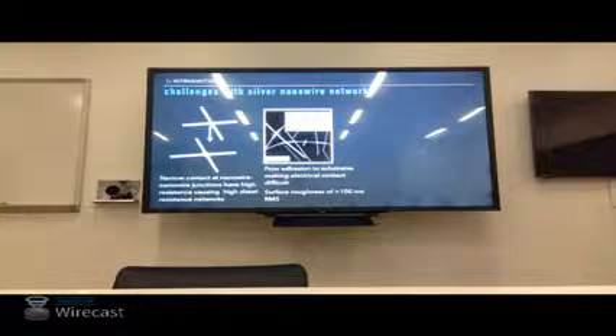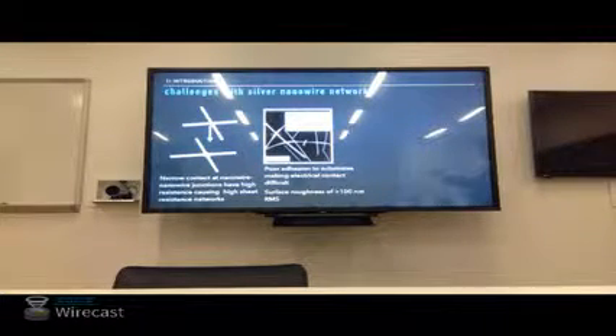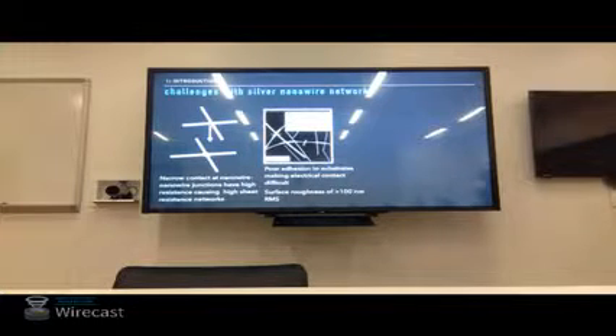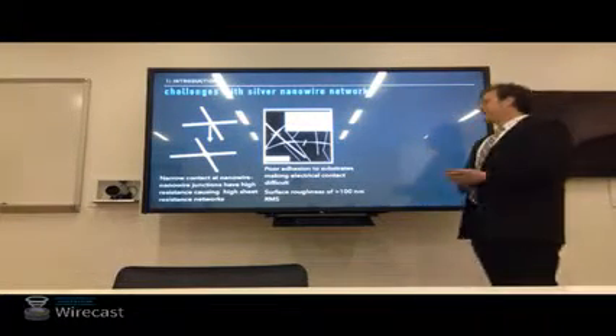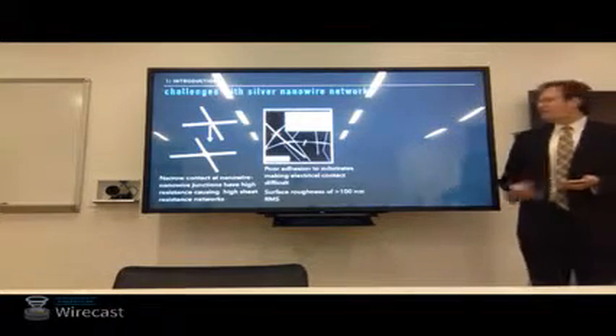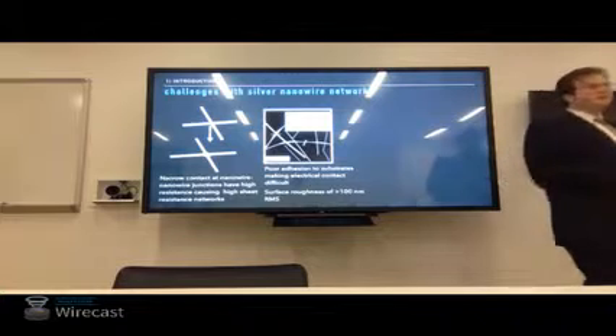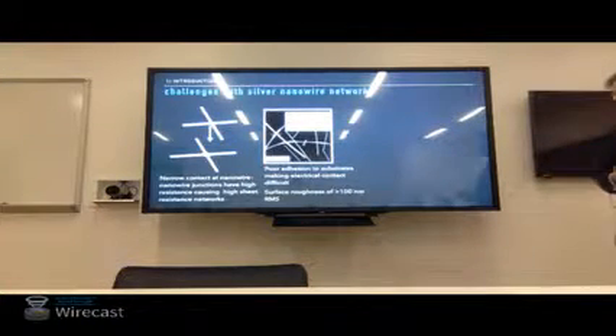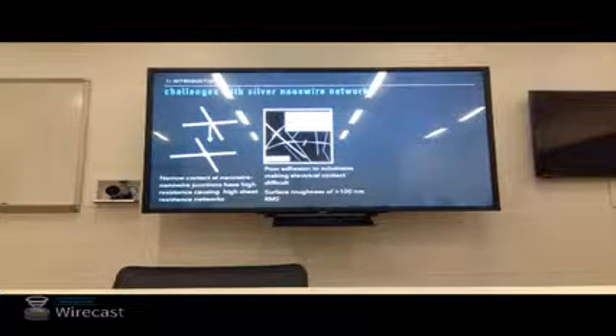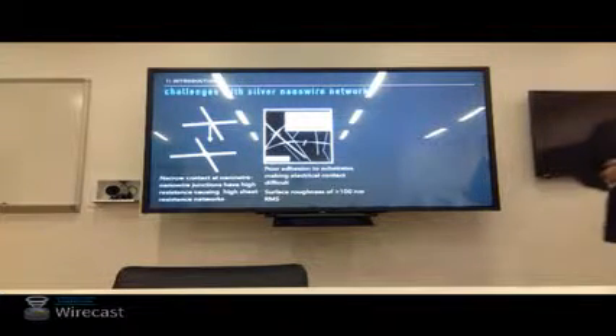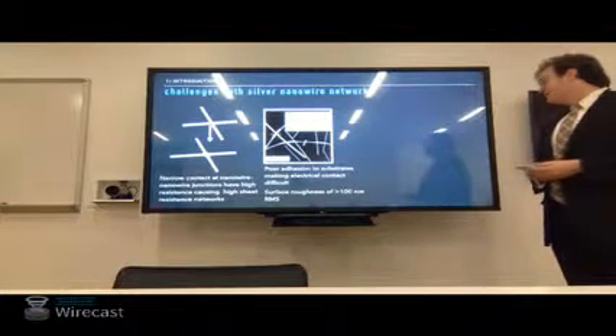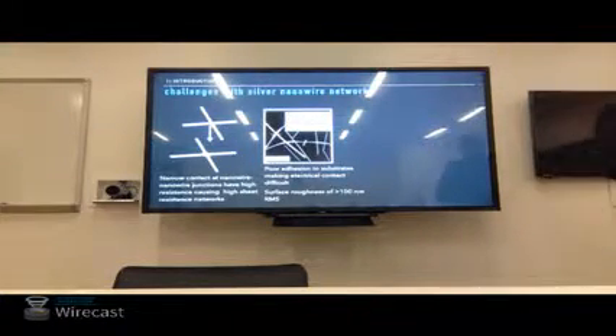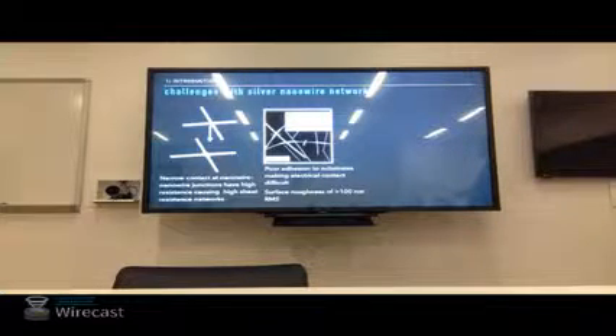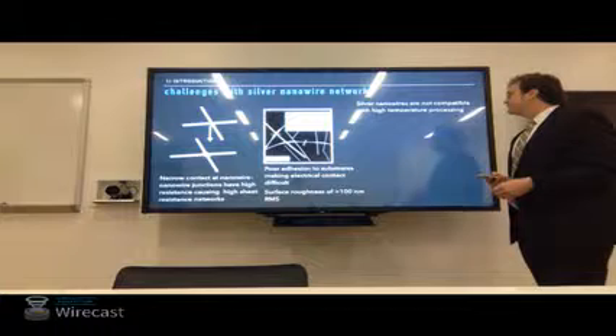Next, we're physically putting, even though it's nanoscale, something that is cylindrical on a flat plane. This leads to poor adhesion. Right? You have these kind of line contacts at nanowires. This is an atomic force microscopy image, showing, as you would expect, I have 90 nanometer diameter wires. I get about a 90 nanometer protrusion when I measure a single wire, and 2 wires about double that. But in addition to poor adhesion, this also makes contacting these nanowires difficult, contacting to the downstream electronics, and it also gives you a surface roughness on the order of the nanowire diameter, which is unacceptable for some processes.